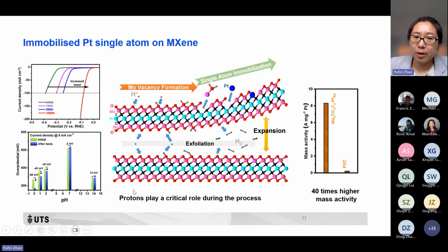And in order to investigate how the exfoliation can occur during this electrochemical process, we assume that the protons may play quite an important role during this process. And we have conducted experiments by using the graphite rod as a counter electrode and conducted this experiment at different pH solutions. We can see in acidic conditions, the performance increased, but the trend decreased when we increase the pH from 0 to 2. That means the high concentration of protons is beneficial for this process.